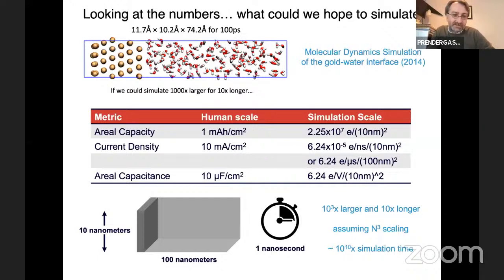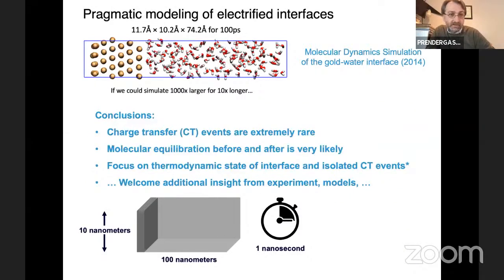So really what we need to do is this concept of constraining our simulations to try to model the details around the events that we might care about. So charge transfer events, they're extremely rare. There's very likely a lot of equilibration that can happen before and after. I'm not really talking about when the current is running, which will create its own steady state, but even just before that point, when you're still in the capacitive regime and you're beginning to initiate charge transfer, you could maybe model that system as a quasi-equilibrium. And so if you focus on the thermodynamic state of the interface and try to isolate the different charge transfer events, maybe that will work.